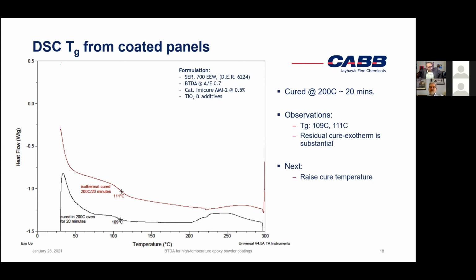Right. So actually, that's exactly what happened. We just wanted a simple 20-minute 200 C conventional cure cycle, just so we know what we get from there. And then we started building different kinds of cure cycles. But now here you have the DSC results, and you start seeing work from Nicola Billick at the Kansas Polymer Research Center. So the bottom curve, the black curve, is the DSC thermogram showing a Tg of about 109 Celsius. And that's from an actual panel that was taken from Kevin's lab. It was cured, so we just chipped off a little piece of that cured coating and put it in the DSC to get this. So we got this Tg of 109.